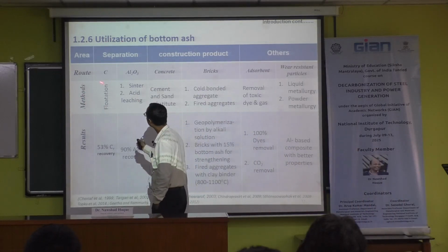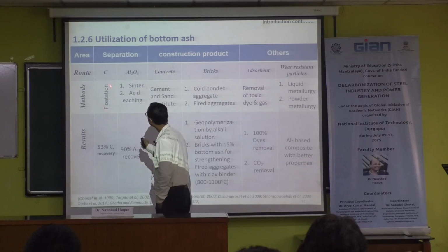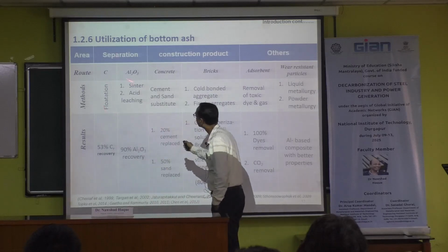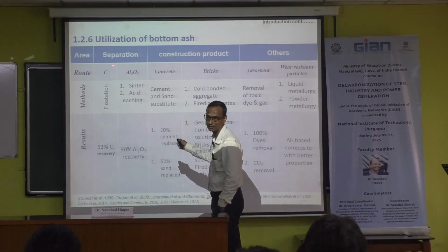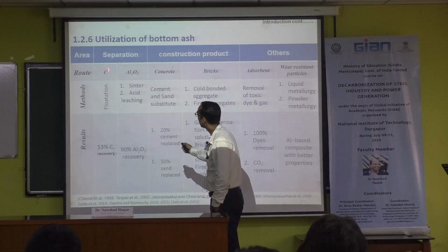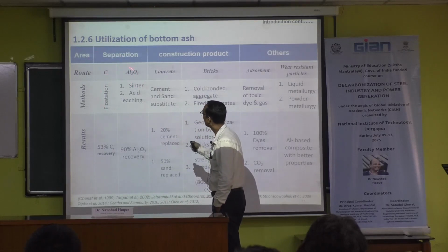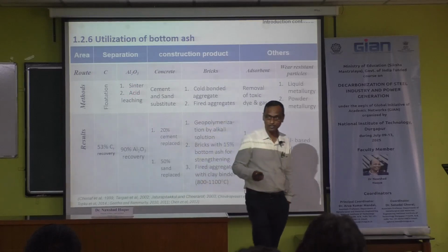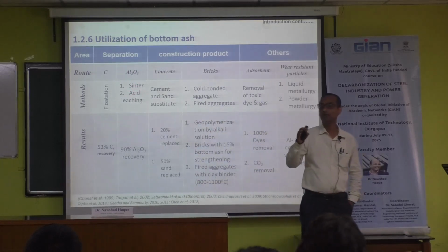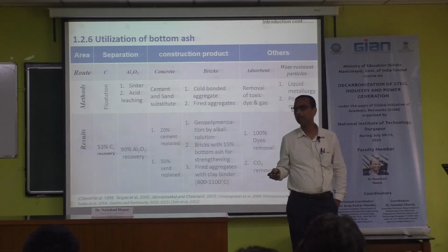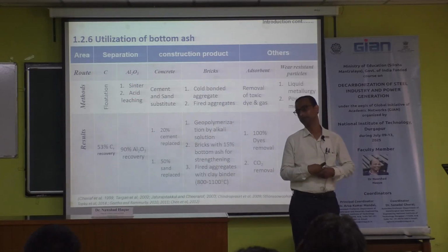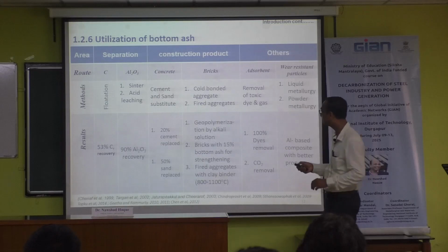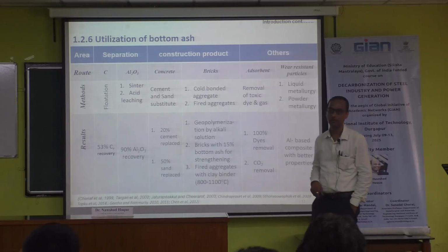What is going on in this area, like the flotation process? They have separated alumina. They have separated carbon by the flotation method. Alumina by sintering and acid leaching. As I told you, the utilization of bottom ash is for extracting the aluminium. In China, the method is called sinter followed by acid leaching, the soda lime sinter process.